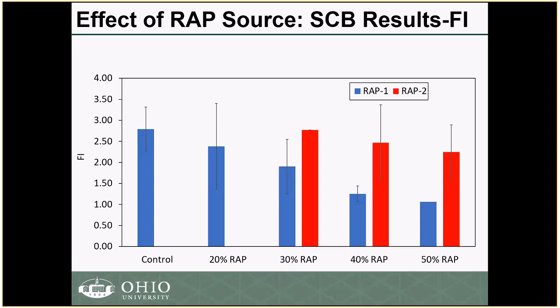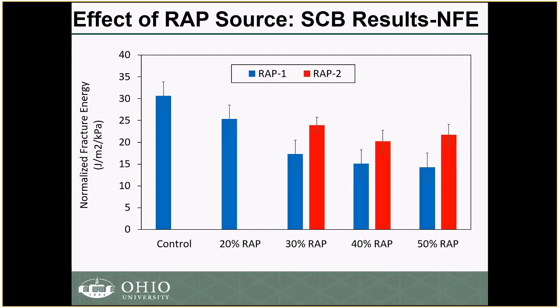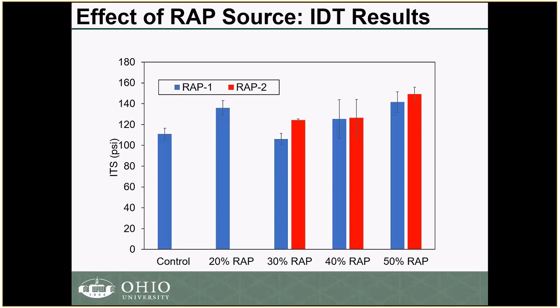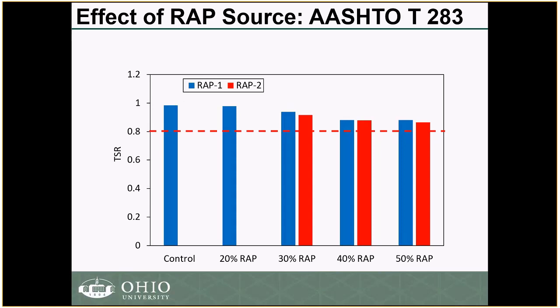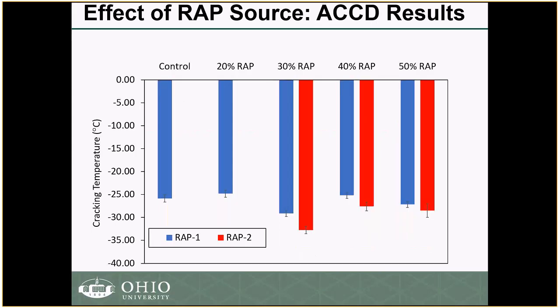And that result is also the same for the normalized fracture energy. There is a considerable difference between both of those RAP materials. For the ITS, there is some difference, but it's not that significant. And again, for the TSR, we did not really see a difference. Both are performing well. For the thermal cracking, there was a difference, and you can see it here, but it was not as significant as the one that we have seen with the fatigue cracking.